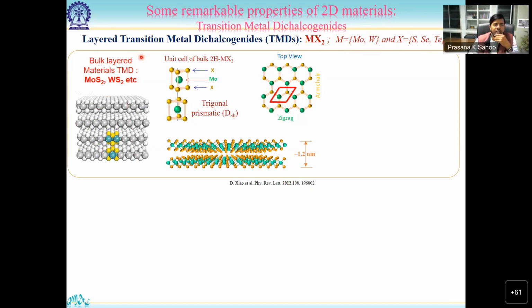If you check the bulk layered materials, in the structure the other layer is inverted relative to the first, like here. So the unit cell of these TMDs is just two layers, and that repeats in space. But it is possible to peel off a single layer, which means a single layer is half of the unit cell. Because of this, inversion symmetry is broken, which gives rise to very interesting properties of this 2D layered material.